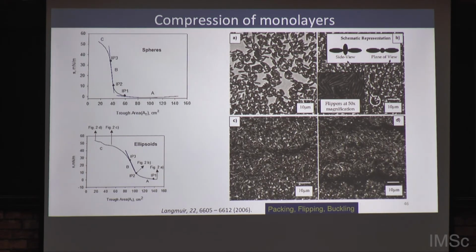Because of that, the reversibility that he was talking about is not going to be there for elliptical particles, because the moment you bring them close together, you are already starting to make particle aggregates. Number one. Number two is that because a lot of particles are lost to the bulk, these transitions are not reversible in that sense. So you would have to start experiments with a fresh monolayer all the time if you really want to see these observations.